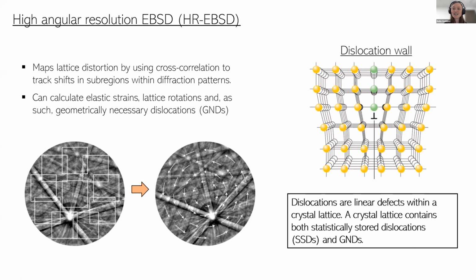We can also look at lattice rotations, which give us an idea of the geometrically necessary dislocations that are within these rocks, which give you an idea of how much they're deformed. Sadly, we can't do that for coesite. We can look at the total number of dislocations in coesite, which I'm going to present in a second. And just to give people who aren't aware what a dislocation is, the simplest definition is that they're linear defects within a crystal lattice. And you can see here I've got a dislocation wall where we've got this extra half plane of atoms. And geometrically necessary dislocations are ones that are necessary to accommodate a strain gradient. So if you imagine you're bending a bar, you have a strain gradient across the bit that's contracting and the bit that's extending. But you also have these things called statistically stored dislocations.